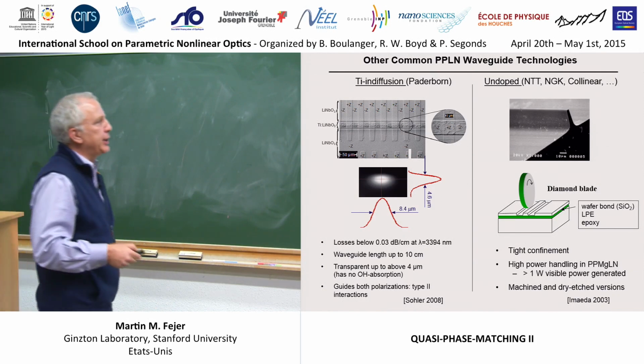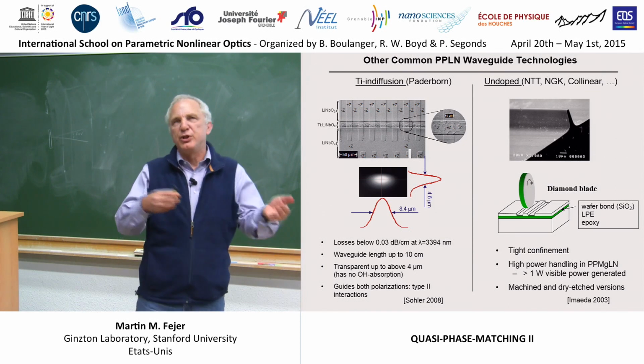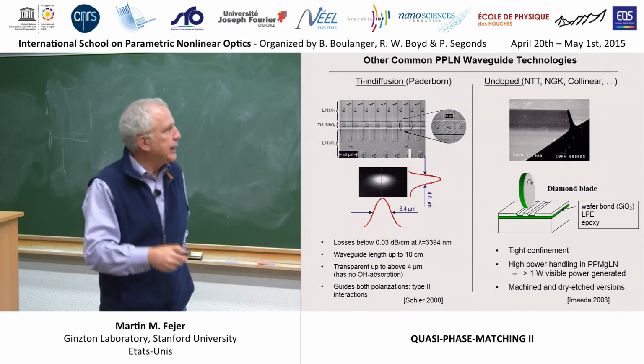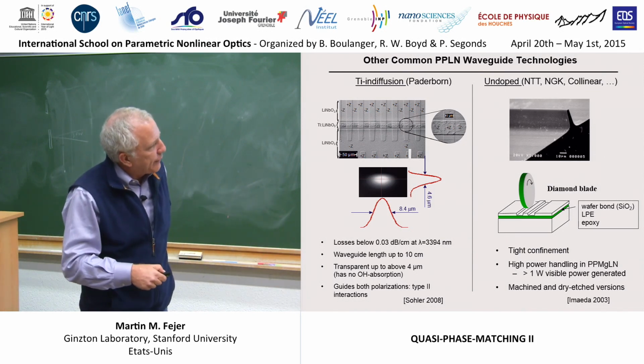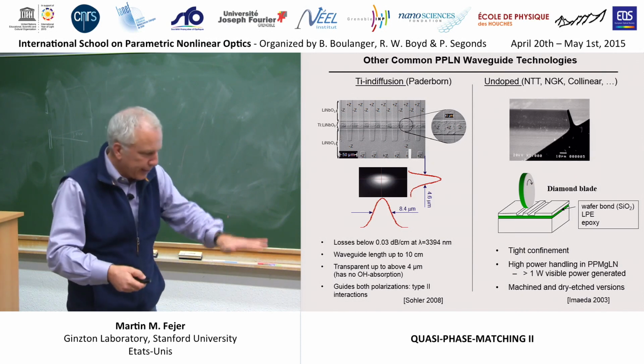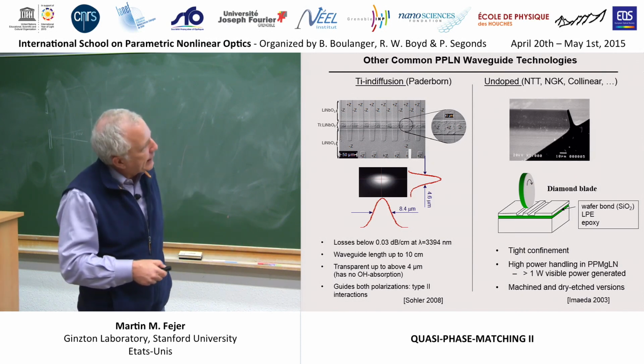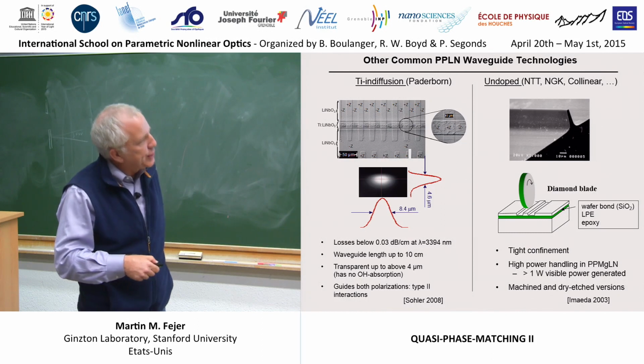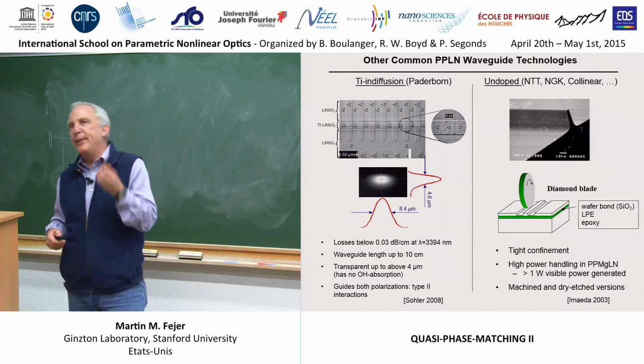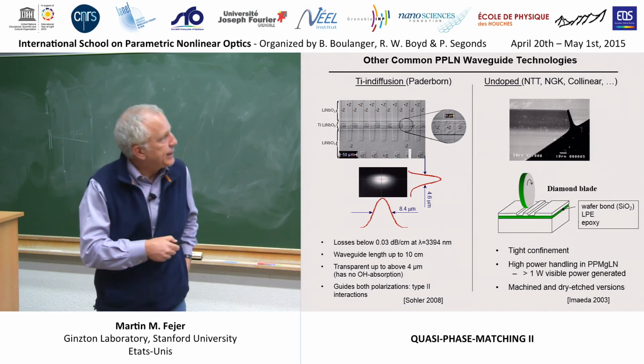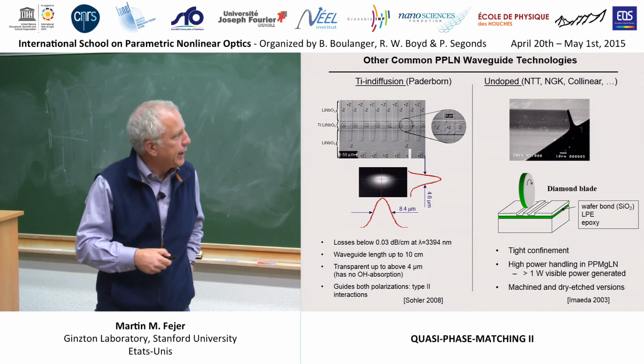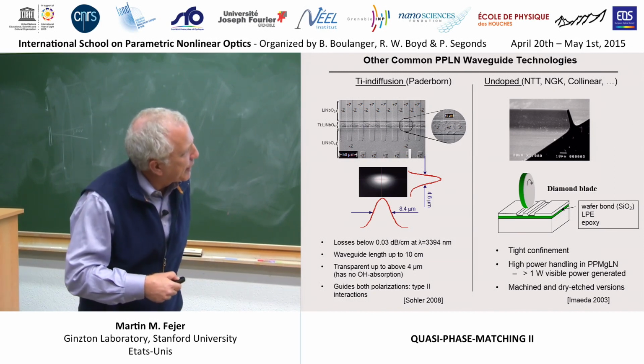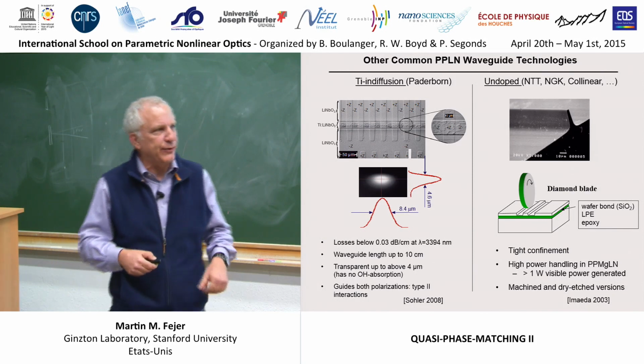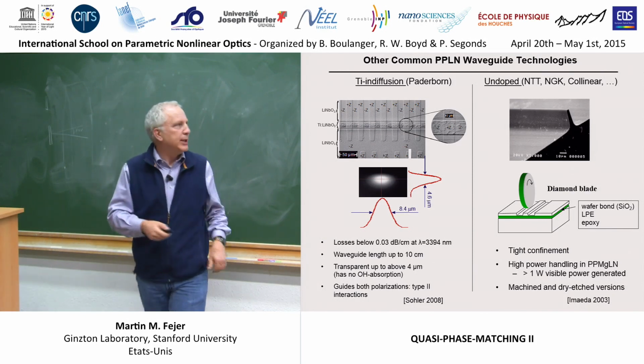The slab is mechanically polished down to a few microns thick, and then a ridge is defined mechanically, either with a diamond saw blade - believe it or not, this edge here came from a diamond saw blade, that's a 10 micron bar you're looking at - so some amazingly smooth surfaces can be generated by these means.